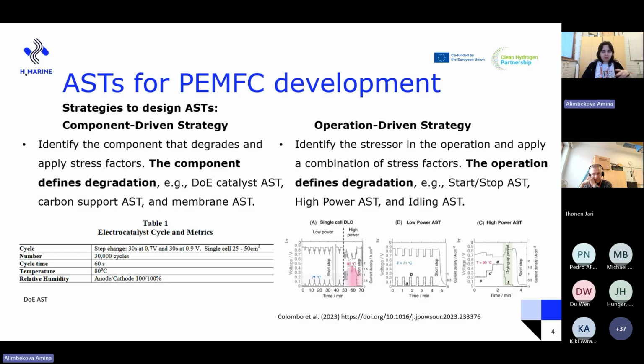The component itself dictates the test parameters for the AST. For example, to isolate catalyst degradation, we would apply voltage potential cycling, as shown in the table from the Department of Energy catalyst AST. But if we want to study carbon support corrosion specifically, we would expose our membrane electrode assembly catalyst to very high potentials or reverse current decay conditions.